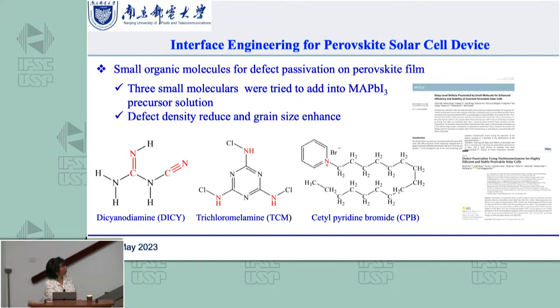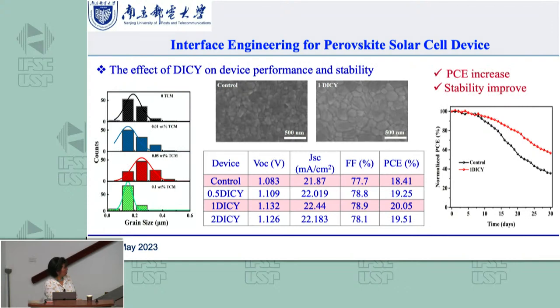Also, we tried to put different materials into the perovskite solution and then directly deposit the solution, and we found it's also possible to improve the PCE, the efficiency, and it can also make the device more stable. So this is some of the work we have done on perovskite solar cells.